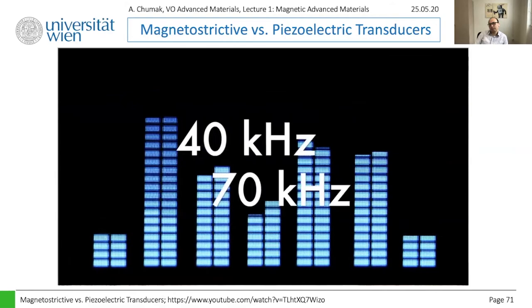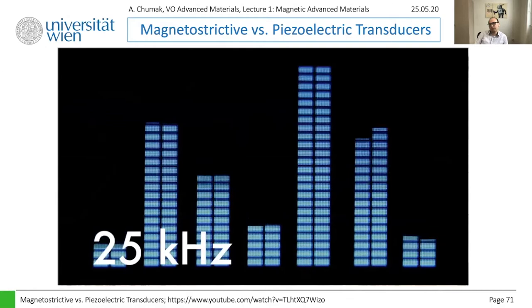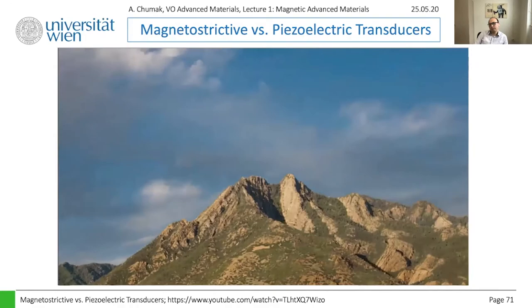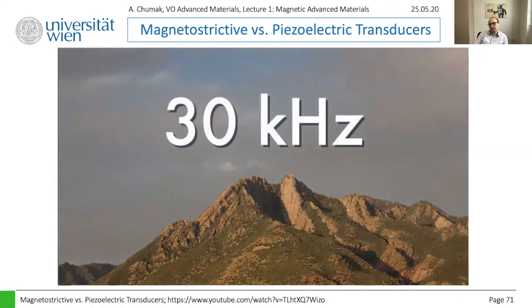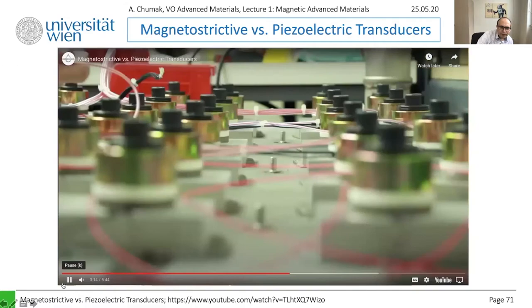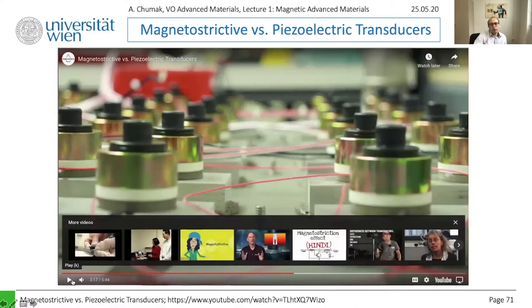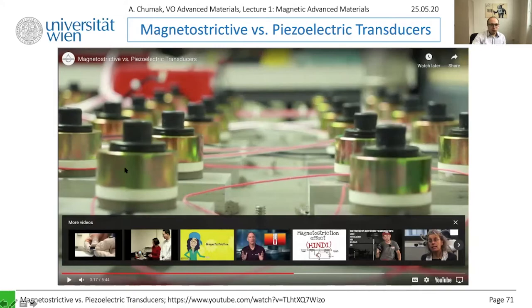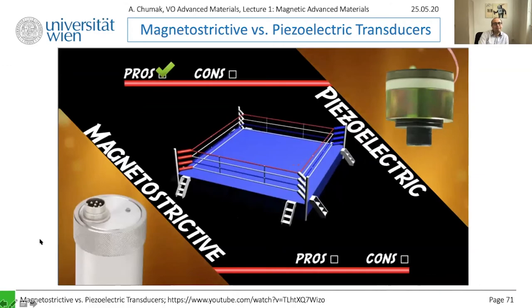For most parts and contaminants, ultrasonic cleaning works best between 40 and 70 kHz, though some cleaners use frequencies from 25 kHz up to 170 kHz or higher. The highest reasonable frequency for a magnetostrictive transducer is around 30 kHz, because to raise the resonant frequency the core must be made shorter and shorter until the mass becomes too low to transmit vibration to the tank. Piezoelectric transducers are not limited by this restriction and can cover the entire frequency range. In the lab, magnetostrictive resonators can operate at GHz range, but only with nano-sized devices, which are impractical for generating vibrations in water.